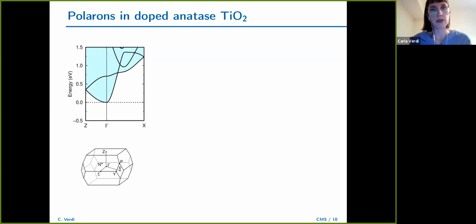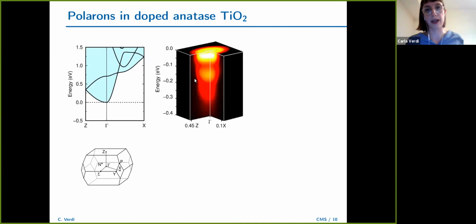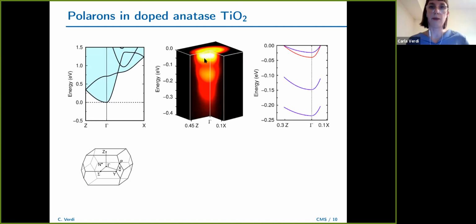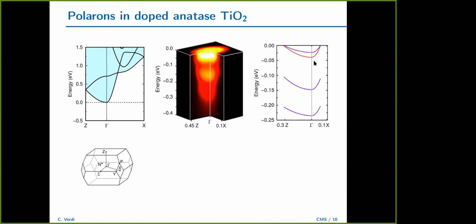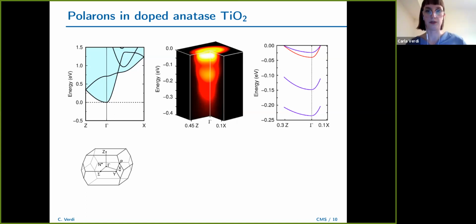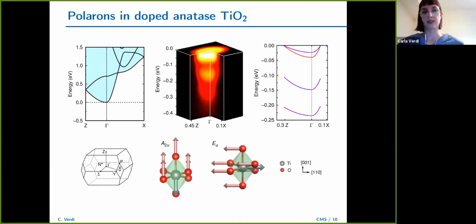So let's move on to some results. We did the calculations on anatase TiO2 as anticipated. This is the bottom of the conduction band of the material, okay? So it is anisotropic. And this is just a sketch of a representative calculation of a spectral function where you see the main peak near the Fermi level and the cascade of satellites. If you track the maxima of these bands, then you can actually get these lines here. So the red line is the unrenormalized band, so what you would get by a standard density functional theory calculation. And then in blue, we have the renormalized band and the satellites as well. And we can actually see from our calculations that these satellites really arise from the interaction of electrons with these longitudinal optical phonons. So there is one which corresponds to an in-plane vibration and another one that is an out-of-plane vibration of the atoms.